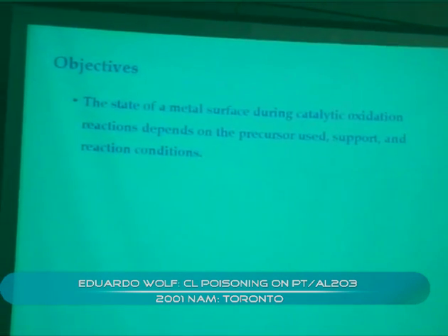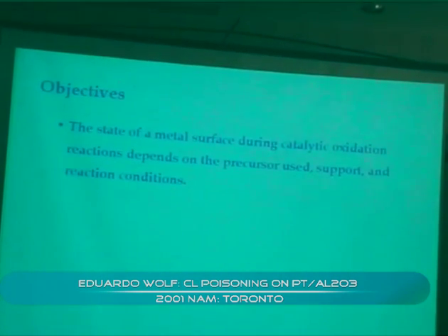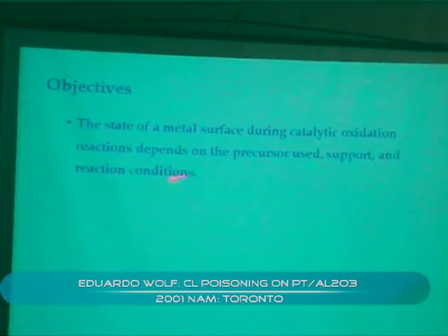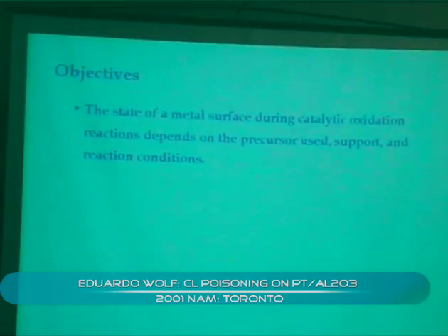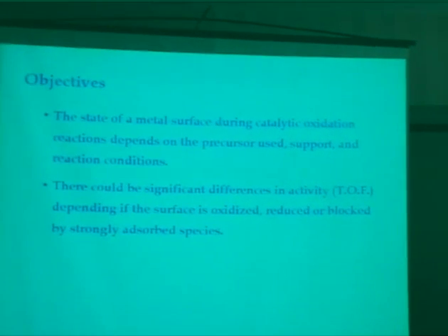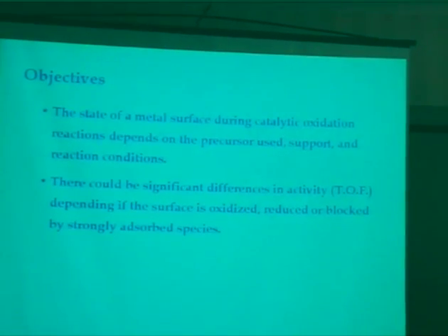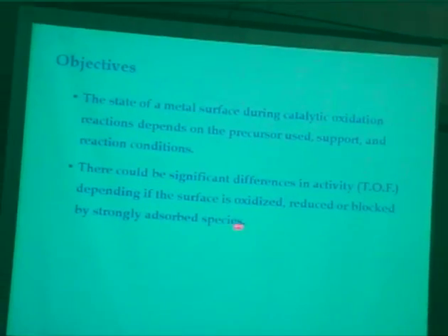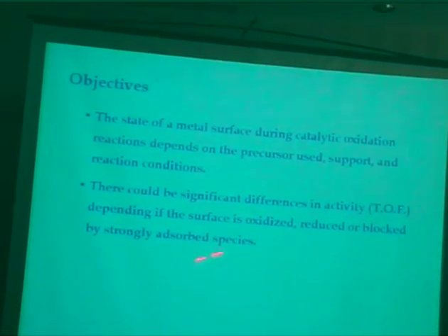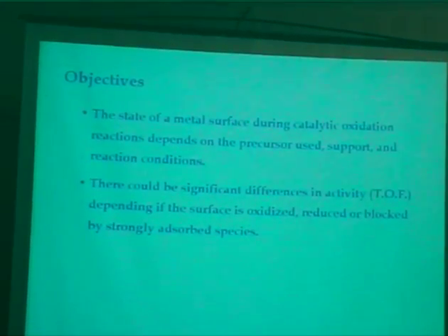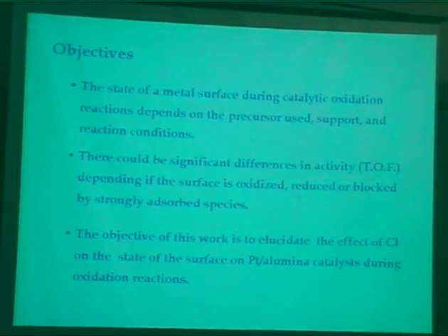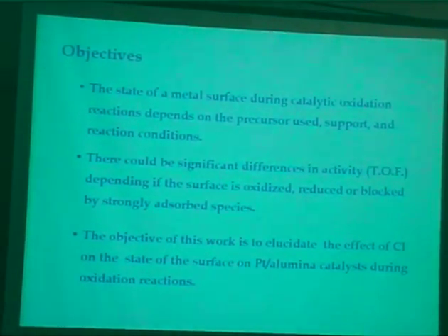For many years, we've been trying to establish that the state of the metal surface is related to how you prepare your catalyst, the support that you use, and the reaction conditions that you use. The problem is, most of the time, we cannot do all these things because the techniques that we use for characterization are ex situ. And we know from the literature data that there are significant differences in activity depending on the state of the surface and if we have adsorbed species. And we just heard of an example where carbon was one of those strongly adsorbed species.